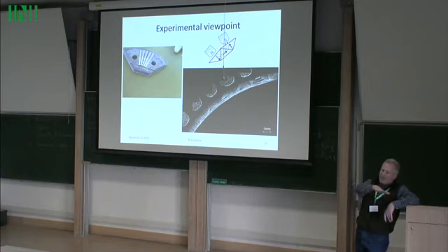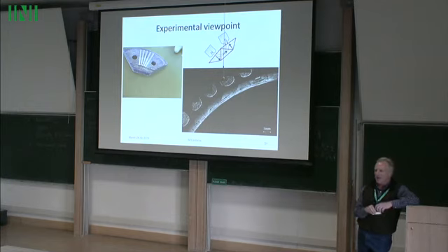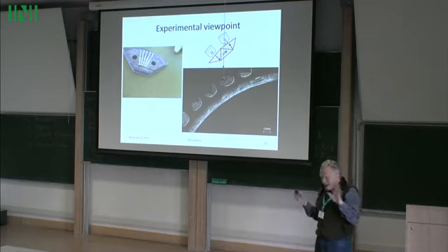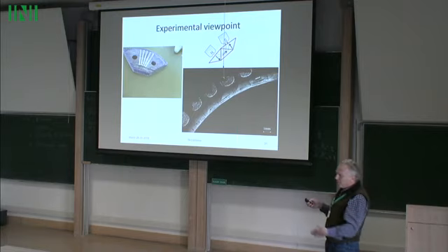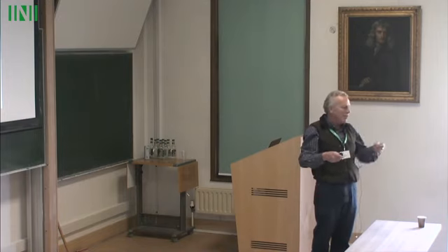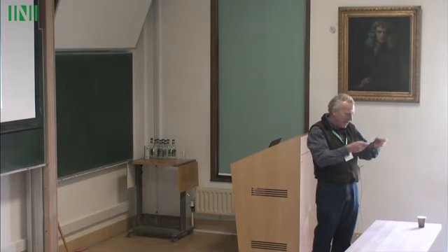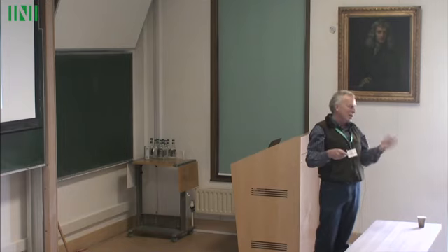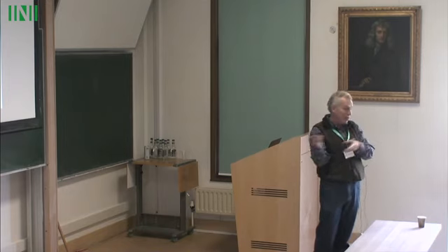And they find, I think it's over something like 7 or 8 orders of magnitude, an incredibly good scaling law with absolutely linear relation. And they interpret it, so I'm not sure I buy it one way or the other, but they interpret this as saying that this material satisfying the cofactor conditions is very easily able to adjust to many different boundary conditions or many different situations.